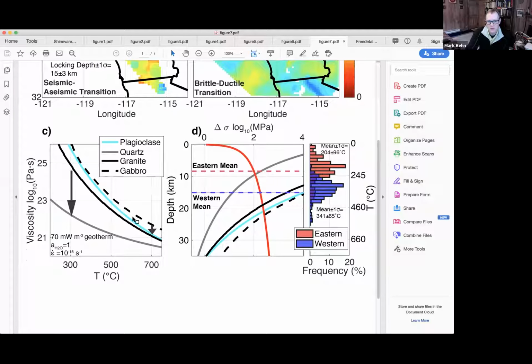So the plagioclase flow law is here. The granite flow law would look about like this if you just assumed a typical granitic composition. Gabbro would sit here. If you compare these in the west, this figure shows depth. This is stress, the predicted stresses that come out of these viscosity curves. And then this red thing is what, in log space, the stress from just a frictional law would look like. And what's pretty interesting is that the western locking depths are pretty well explained by a granite-gabbro dominated rock.